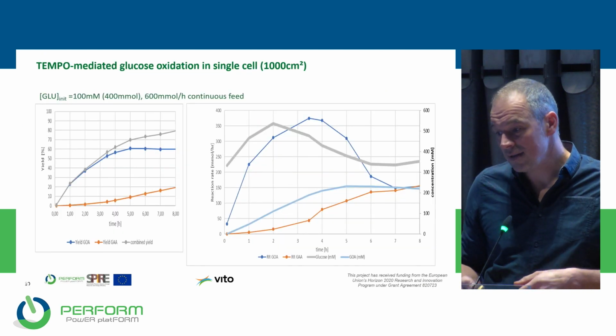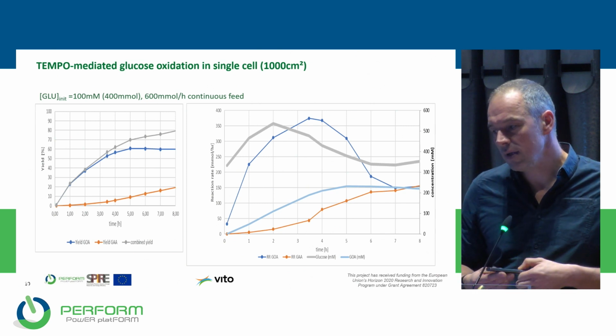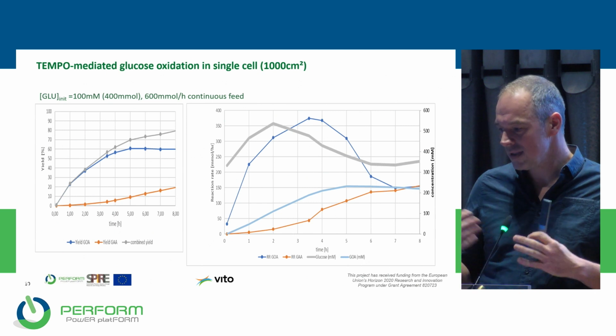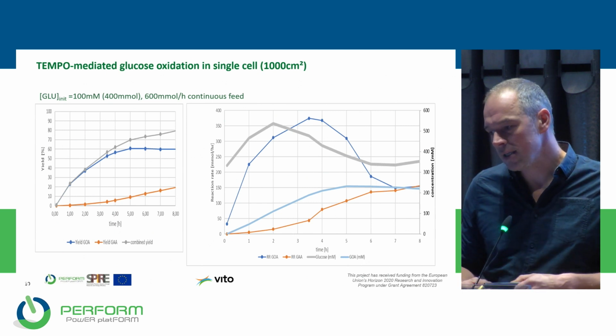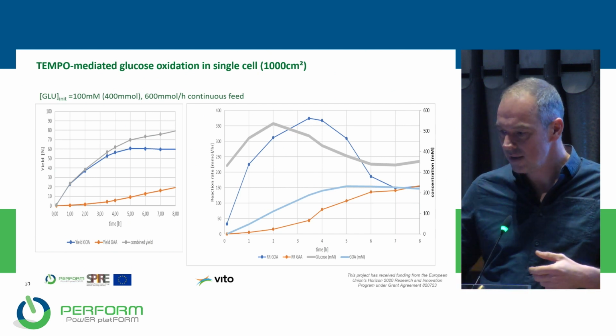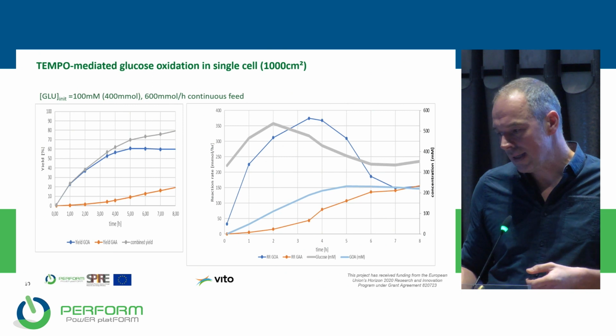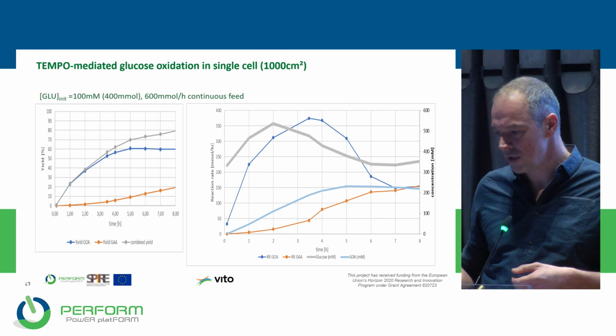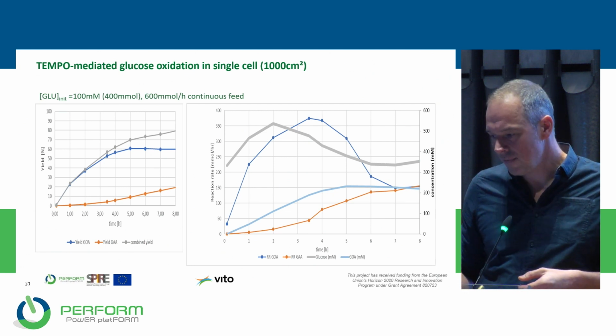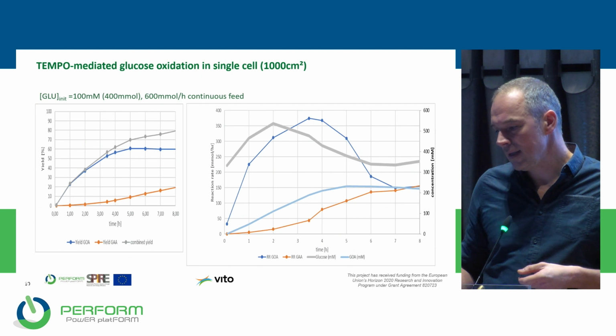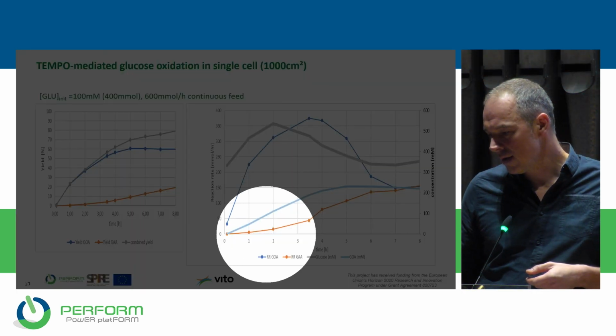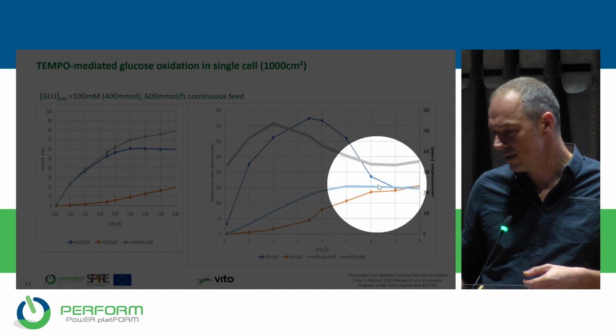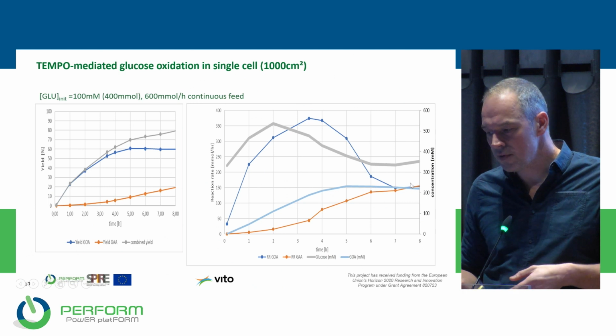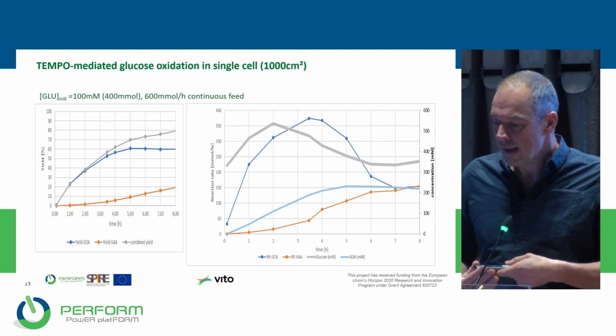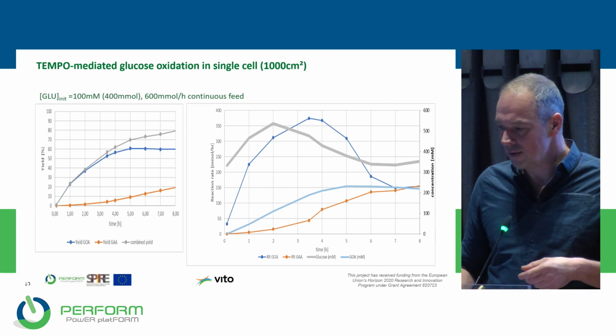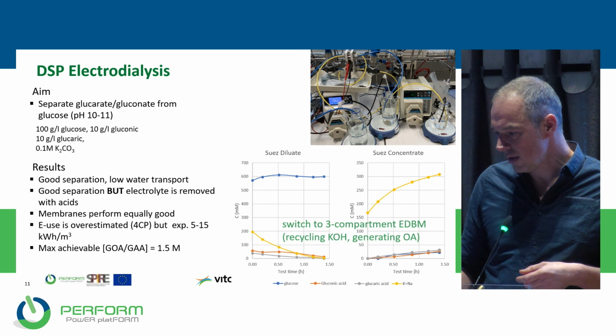So at a continuous feed of glucose, actually, this is not a batch experiment anymore. This is really a feed and bleed experiment where we use the big cell and continuously feed glucose. You can actually see quite nicely the evolution here of the glucose level, which is still fluctuating, but let's say fairly constant. And you can see in the right graph the reaction rate of the glucaric acid is still increasing. The blue line indicates the reaction rate of the gluconic acid, the first step, which is decreasing while the glucaric acid is still increasing. Very nice.